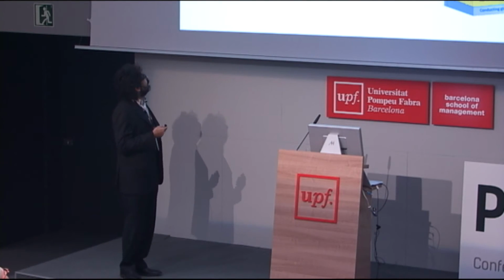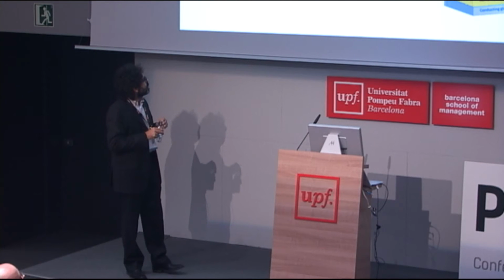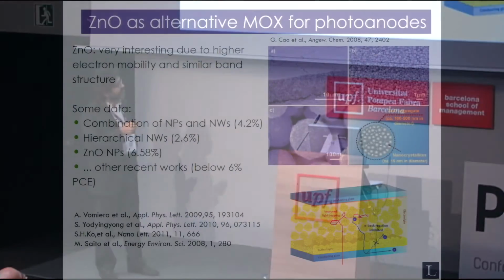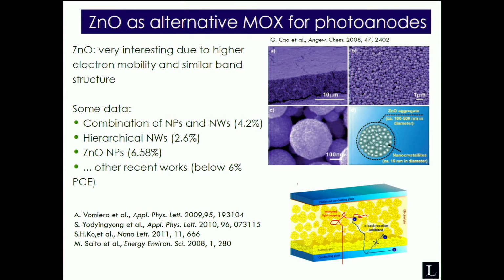Another example of how to manipulate nanomaterials is the case of zinc oxide hierarchical structures. In this case, we capitalized on this kind of micro beads that are composed of very small nanoparticles. This system is very intriguing and interesting because it has a very high specific surface given by the nanoparticles, and at the same time the large dimensions of the grains make the system highly scattering.